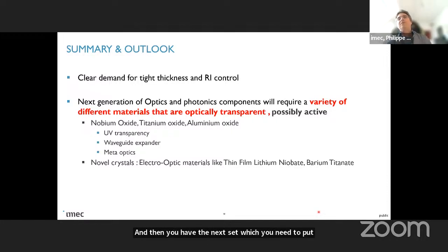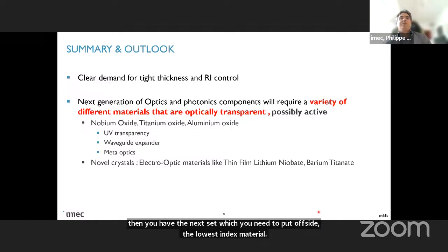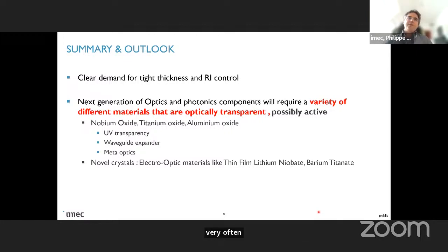And that oxide, it's not very often cited, but sometimes induces as well optical losses, because the people that work on these depositions add their ingredients, the precursors and so on that are typically used in CVD processes, and they also induce losses. Niobium oxide, titanium oxide, very important for us for the upcoming platform. We have demonstrated niobium oxide as well as a waveguide. The losses are not yet at the level of what we can reach with silicon nitride, but are today maybe in the range of what you can do with crystalline silicon.